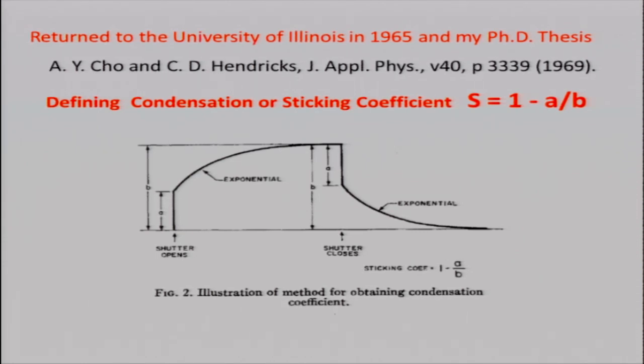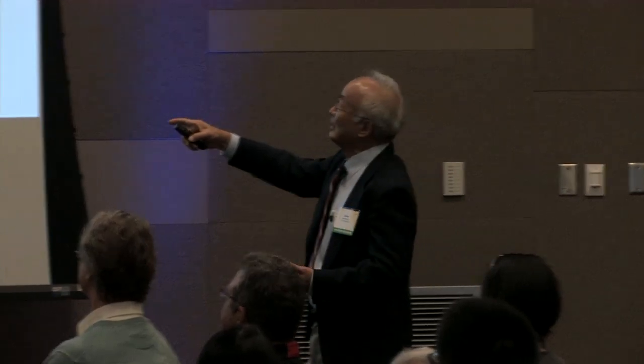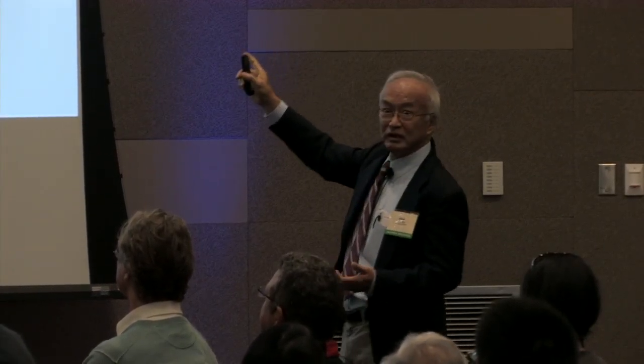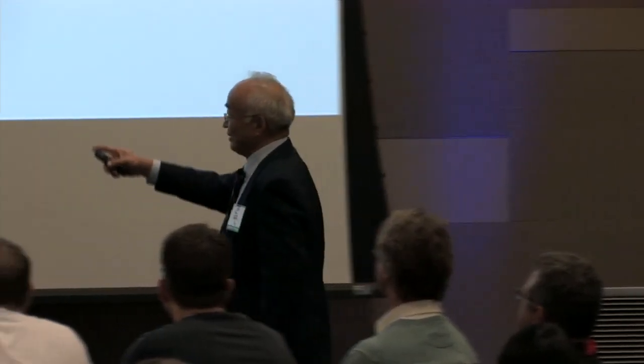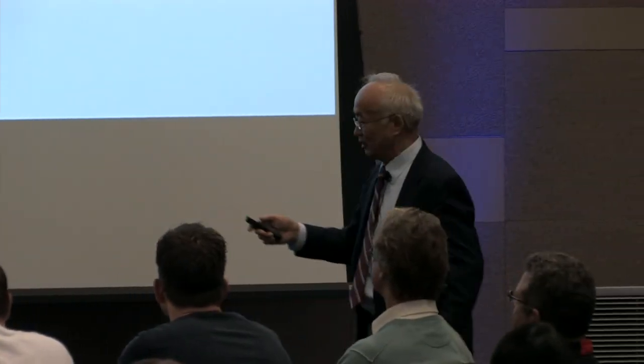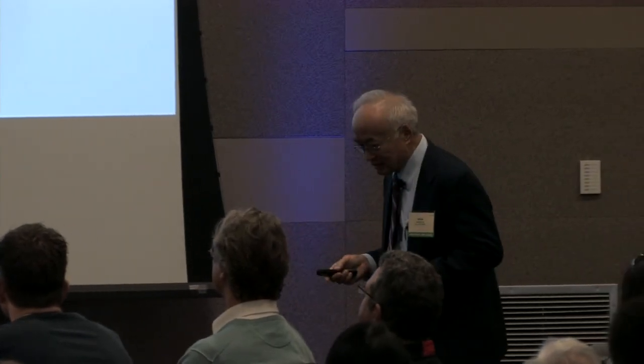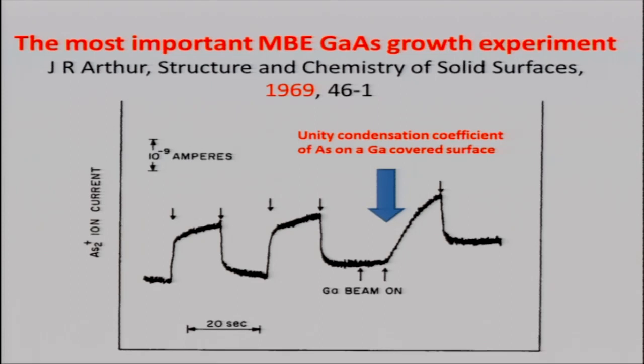Look at the two extremes here. If A equals B, then the sticking coefficient is 1 minus 1, which is 0. That means no atoms are absorbed on the surface. The other extreme, if A equals 0, then the sticking coefficient S is equal to unity, 1. That means every atom you hit on the surface sticks. And of course, in between there can be a fraction absorbed, 0.2, 0.5, and so on.